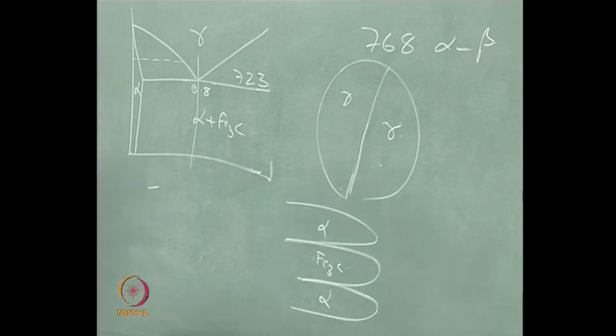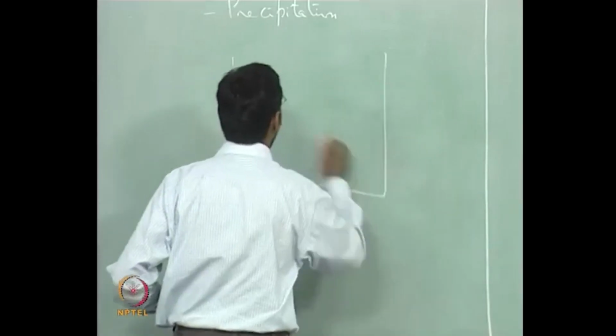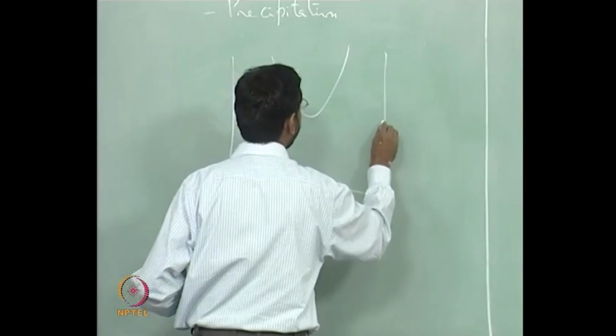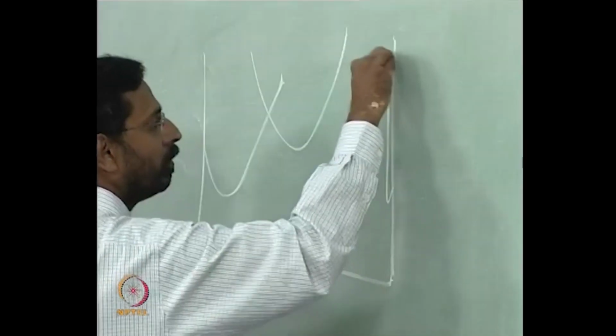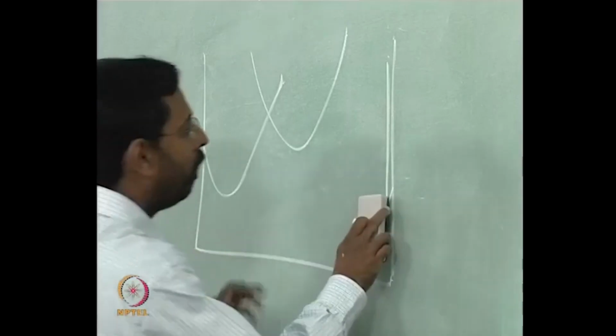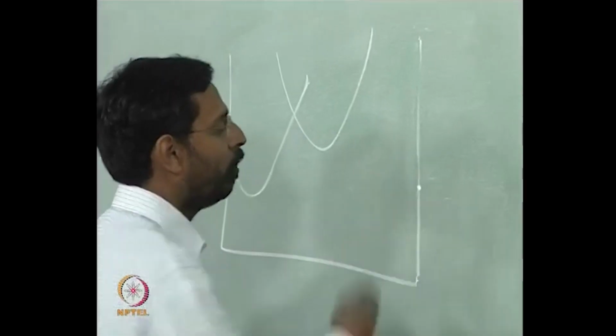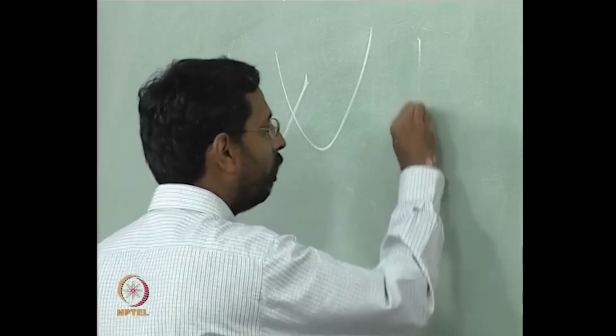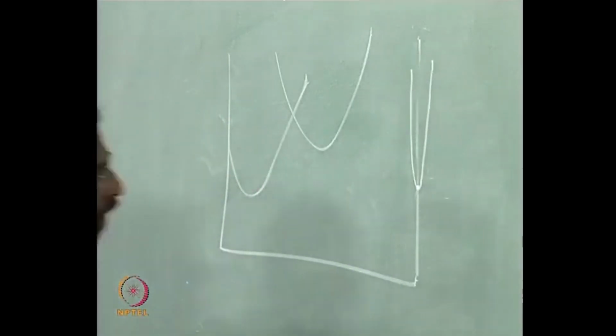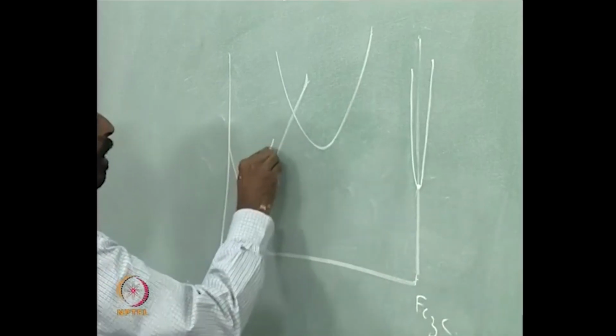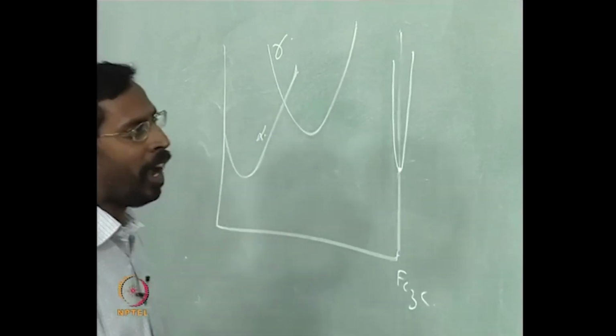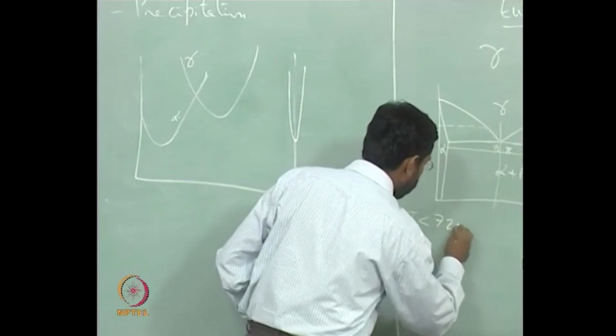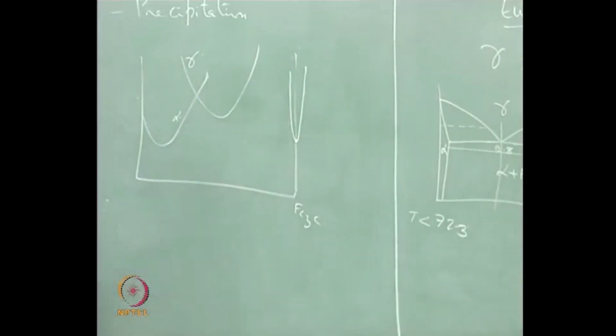Why do they accumulate? Because I am at a temperature at which gamma is not stable. How do I again look at it? I can draw the free energy composition diagram for it. If I draw the free energy composition diagram, I have the gamma here, I have the alpha here, I have the cementite somewhere here. This should in principle be a dot, and if you want to show it, you can show something like this. And if I call this cementite, and this is alpha, this is gamma, and if I am at a temperature T less than 723, then only this free energy composition diagram is valid.